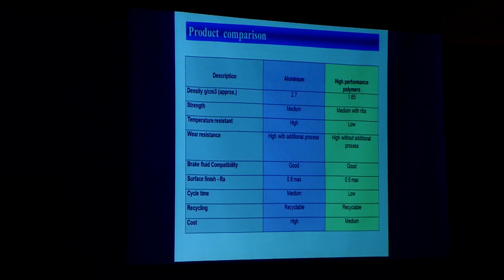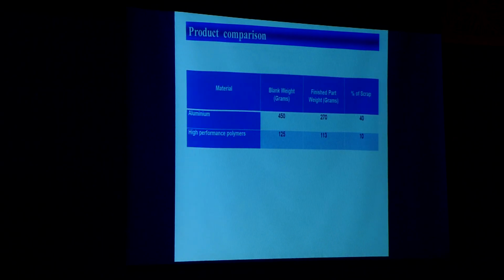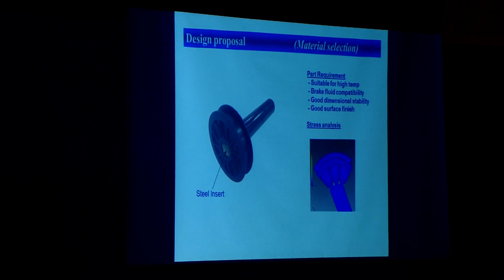Again, the product comparisons were made with aluminum and with identifying the high performance polymers: density, strength, temperature resistance, wear resistance, brake fluid compatibility, surface finish, cycle time, etc. In terms of blank weight, the aluminum was 450 grams, finished product weight was 270 grams, while the high performance polymer nylons were chosen for this. The finished product weight was 113 grams. There's a substantial cost reduction, substantial material weight reduction in this. Again, required for high temperature, fluid compatibility, dimension stability, and surface finish.